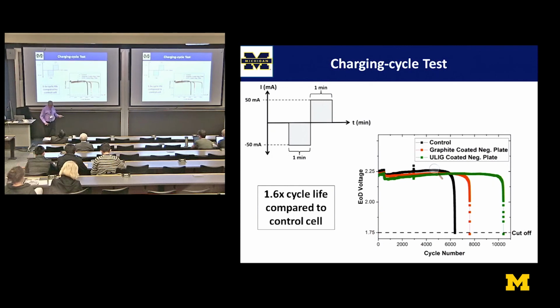to improve the coatings on electrodes for batteries. So the idea here is take a battery electrode, coat it with graphene so that it can store more charge and so that charge can enter the battery more easily, and so its cycling would be improved. So we've improved the cycle lifetime of a battery by a factor of 1.6, which is huge,